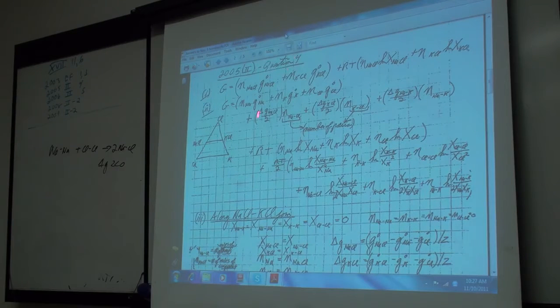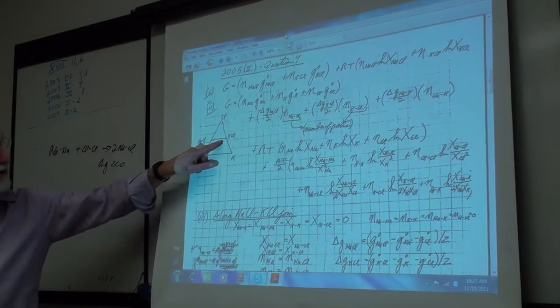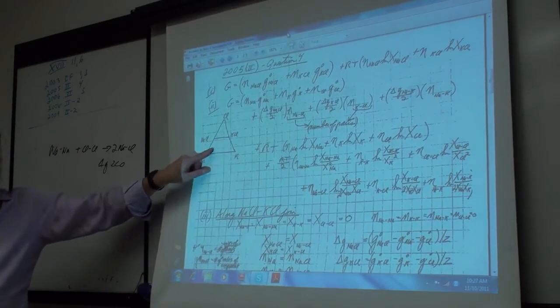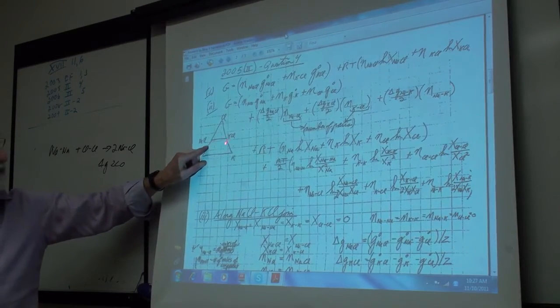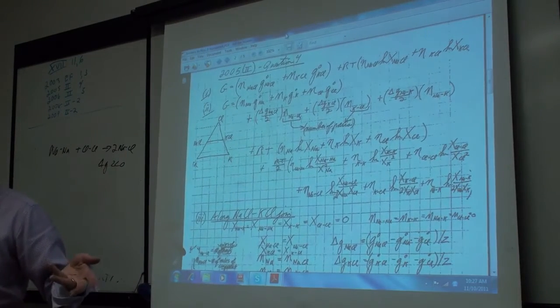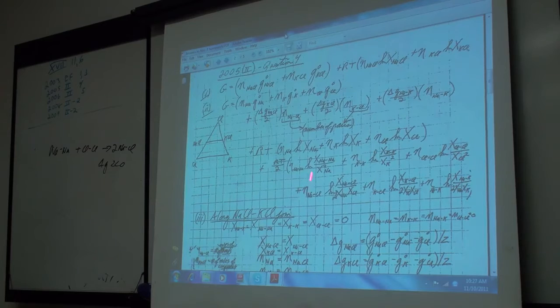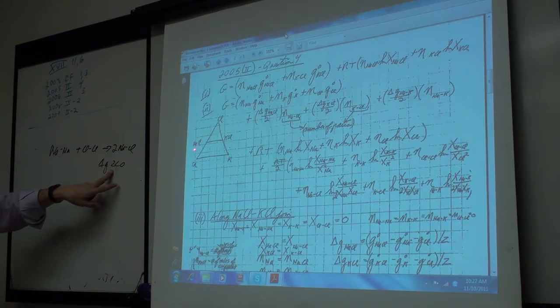Now, then we're going to take this equation along this join, so I'm going to apply it just along the sodium chloride, potassium chloride join. And I'm going to make these delta G's of forming these bonds here, NaCl and KCl bonds, very, very negative. So I'm going to make the substitution in here that this reaction to form the sodium-chlorine bonds and the equivalent one to form the KCl bonds are extremely negative. And I'm going to apply it just along that line.